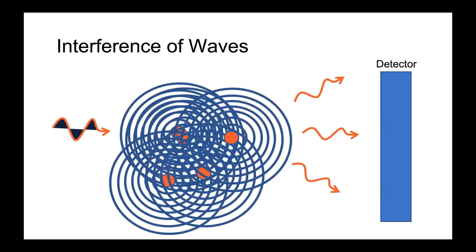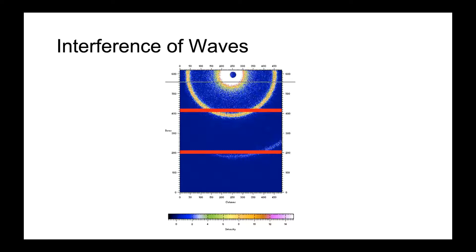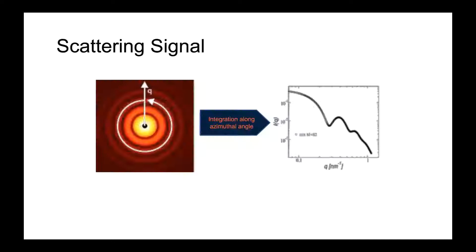With a much larger ensemble, you get a lot more interference as a function of where electrons are relative to each other. All those constructively interfering waves eventually make it to the detector, relaying structural information. Once detected, you end up with a two-dimensional scattering pattern. In the center is the beam stop, and surrounding it are scattered waves at very small angles — you get a peak that is isotropic, indicative of your structure.